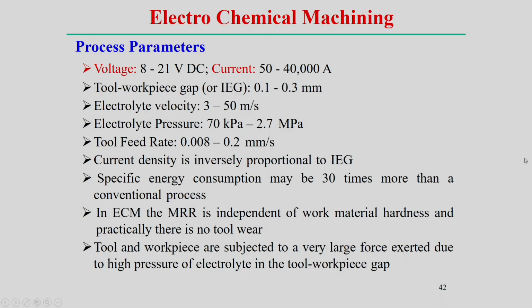What are the process parameters normally followed here? In this case, the voltage is normally 8 to 21 volts. Normally DC current is used, which can be from 50 to 40,000 ampere. For the tool-workpiece gap, the inter-electrode gap can be 0.1 to 0.3 millimeter. So, that gap is very small in these cases.